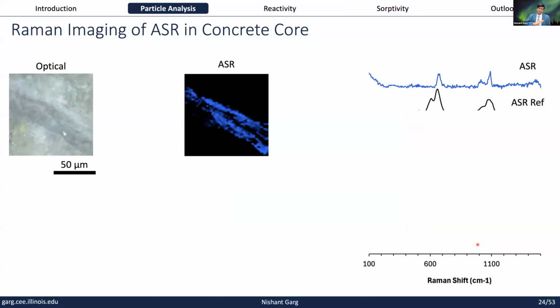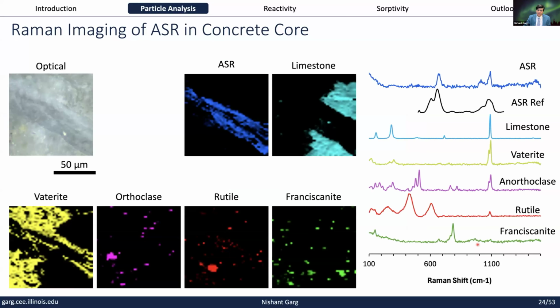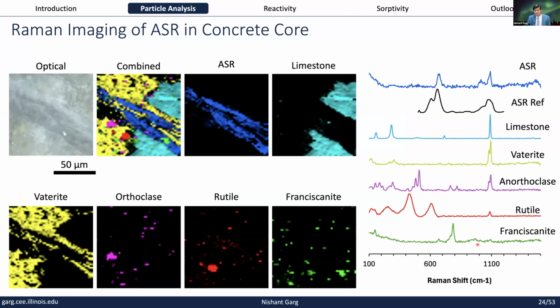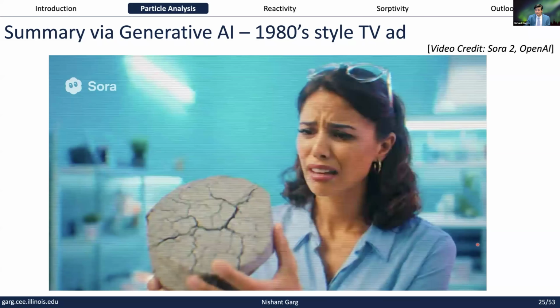with Raman imaging. And what we find is that if you create a hyperspectral image, you can start to see the ASR signal quite well. It's going through what seems to be a limestone particle, and there's a vaterite particle on the left side. And we can now finally start to map it because the spectra, even though they're broad, have clear signals for that from the literature. So one of the things I wanted to do is summarize this issue of looking at ASR with Raman imaging using generative AI. So I showed you a picture of a generative AI image, but here's a full video that I created using the Sora app. So I'm just going to play it here.